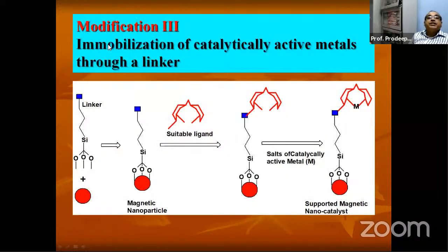So this is modification 3: immobilization of the catalytically active metals through a linker. So this is actually the one mostly people use. I'll explain this. First you take a linker, then of course you have to synthesize the nanoparticle. This is a nanoparticle. Okay. Then this linker, through this particular orthosilicate, you put this on the surface of the nanoparticle.